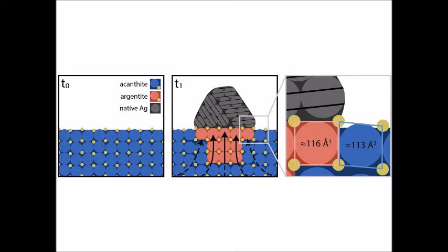Now, the rate of migration or conduction is so fast that as these atoms organize themselves on the surface, many defects are created within the crystals, and those defects are essentially grain boundaries. So this represents one crystal here, and there's another crystal here, and we believe that it's the rate of ion migration and the formation of the wire that leads to the polycrystalline texture.